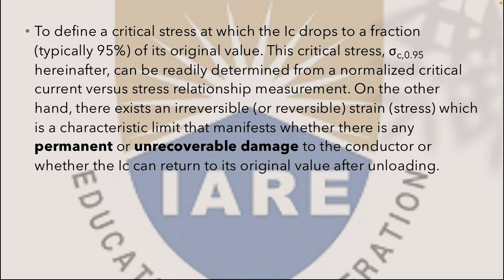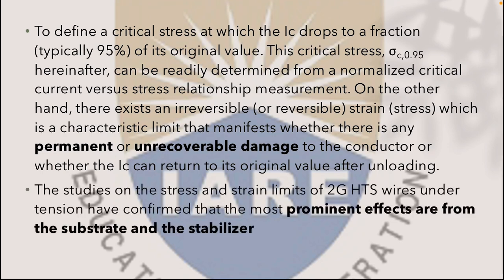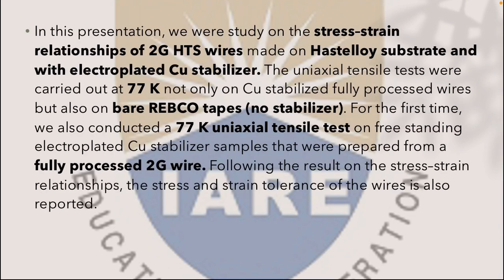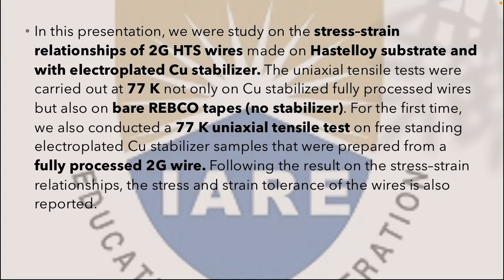On the other hand, there exists an irreversible stress and strain, which is a characteristic limit that manifests whether there is any permanent or unrecoverable damage to conductors, or whether the Ic can return to its original value after unloading. The studies on the stress and strain limits of 2G HTS wire under tension have confirmed that the most prominent effects are from the substrate. In this presentation, we study the stress-strain relationship of 2G HTS wire made with a Hastelloy substrate and the electroplated Cu stabilizer.